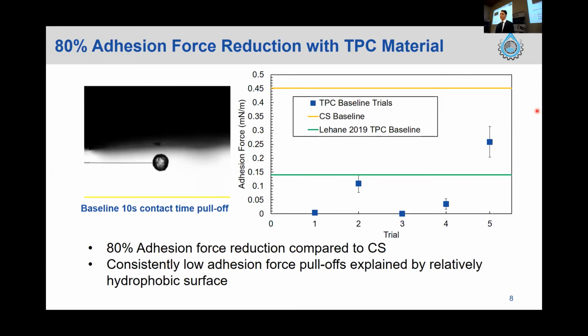So basically what you can take out of that figure, which is quite visually obvious, is that the TPC adhesion for each of these trials was well below that for the carbon steel. And in fact, the mean TPC adhesion was an 80% reduction, as mentioned previously. And just for comparison also, Lehane's TPC baseline on a non-water saturated system is plotted here, which agrees closely with my results. And basically that reduction in adhesion force for the TPC in comparison to the carbon steel was explained by a relatively hydrophobic surface.